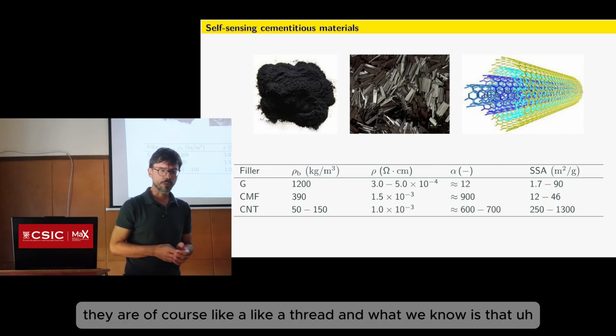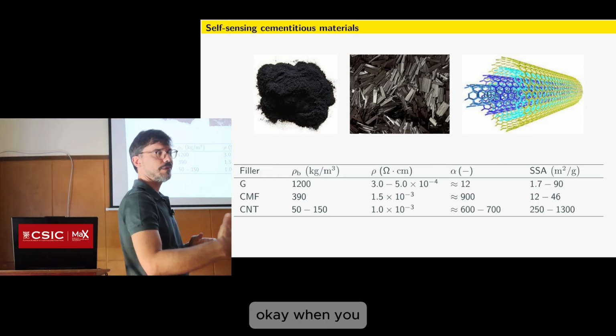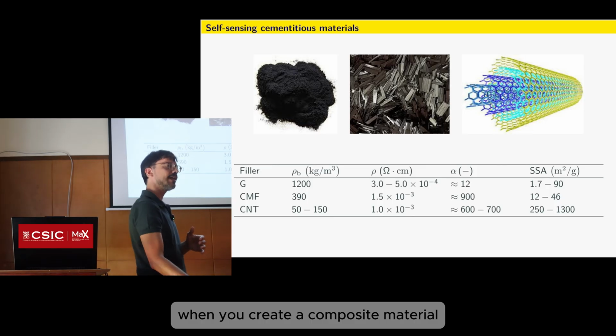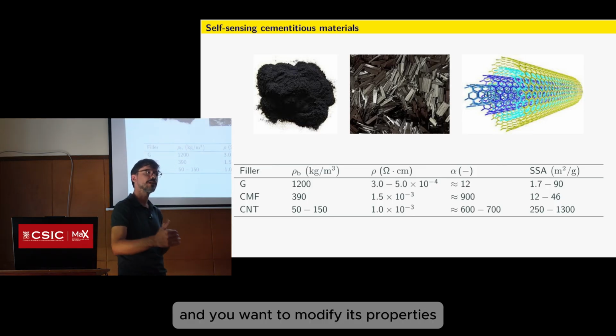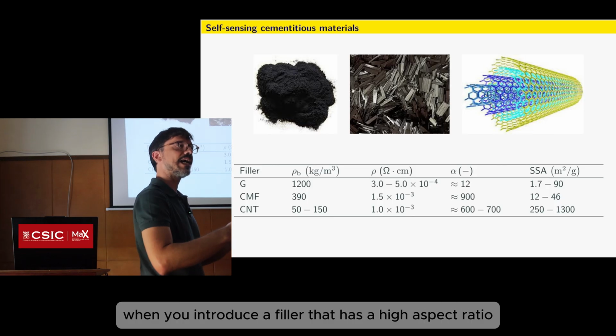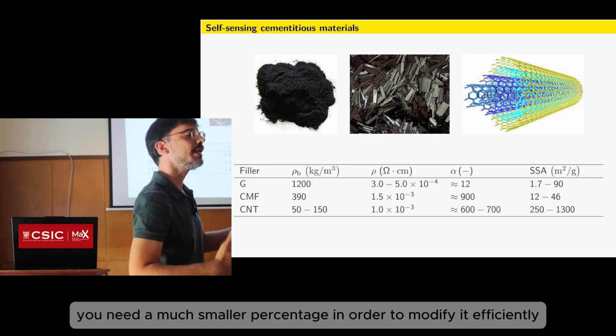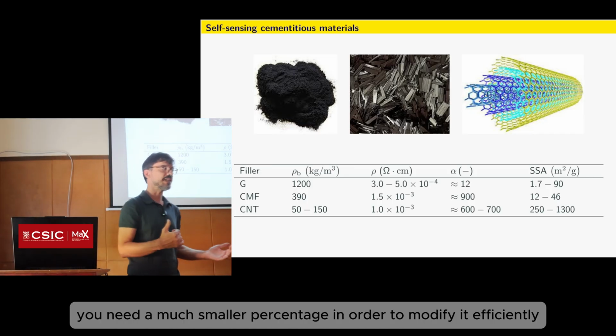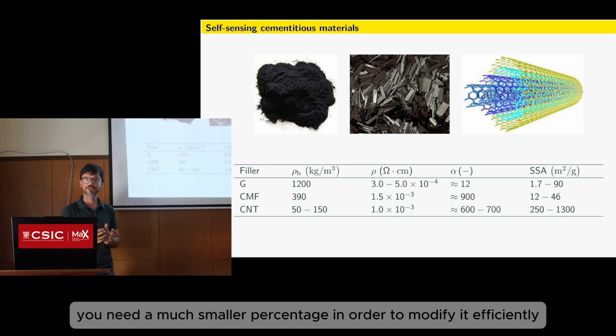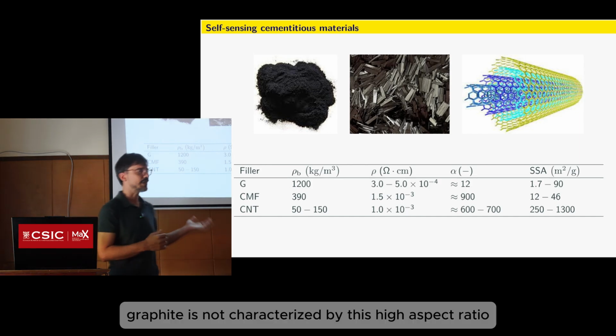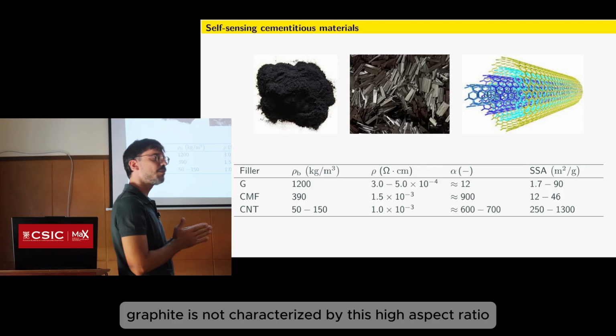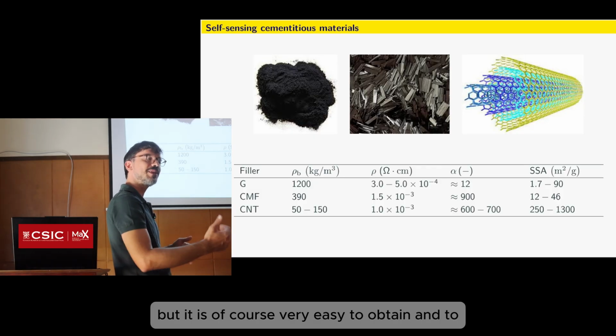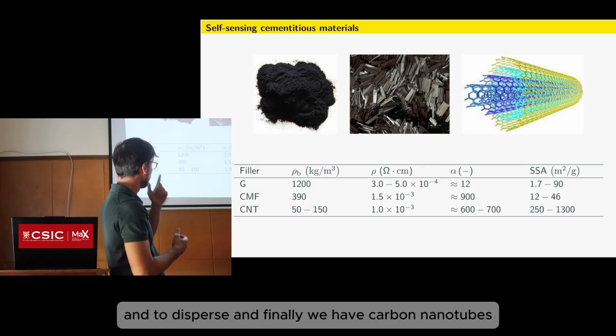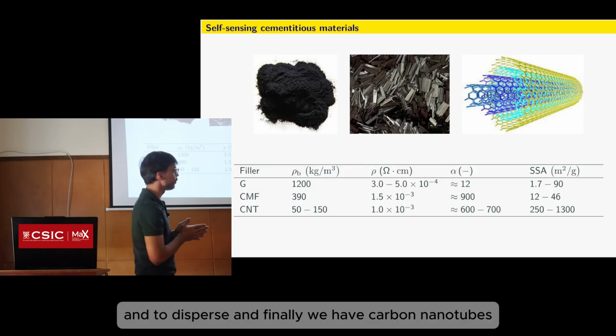And what we know is that when you create a composite material and you want to modify its properties, when you introduce a filler that has a high aspect ratio, you need a much smaller percentage in order to modify it efficiently. Graphite is not characterized by this high aspect ratio, but it is of course very easy to obtain and to disperse. And finally, we have carbon nanotubes,